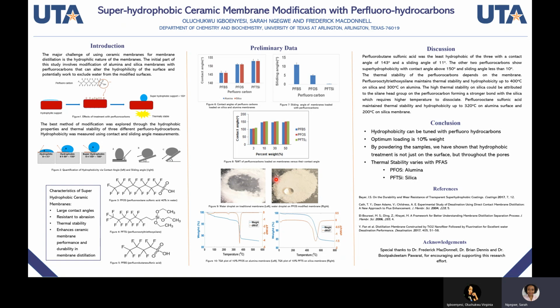This is an image of hydrophobic modified membrane crushed into powder. As you can see, the water beads on the surface, and this indicates the superhydrophobic nature of this membrane. And also, this shows that the modification is not just on the surface, but also within the pores. Here is a traditional hydrophilic membrane, which is completely wetted by water, crushed into powder.